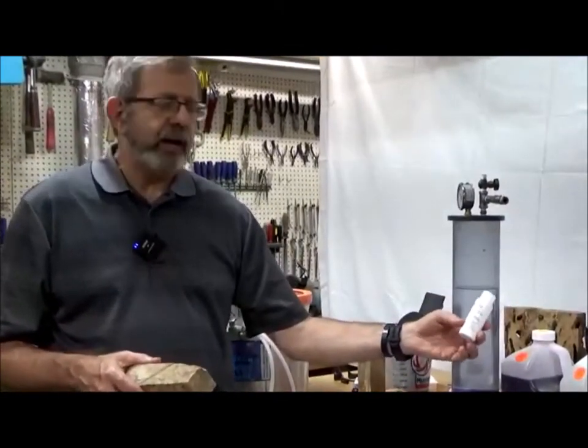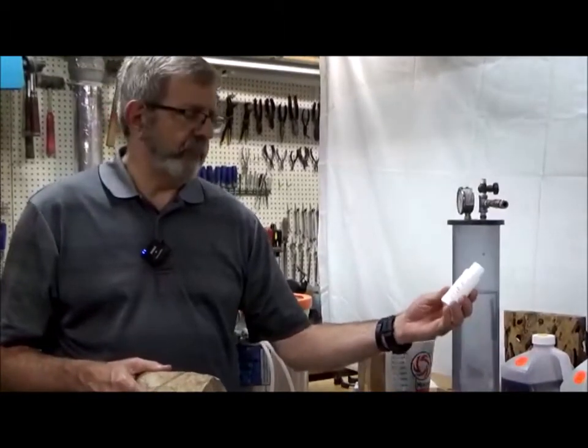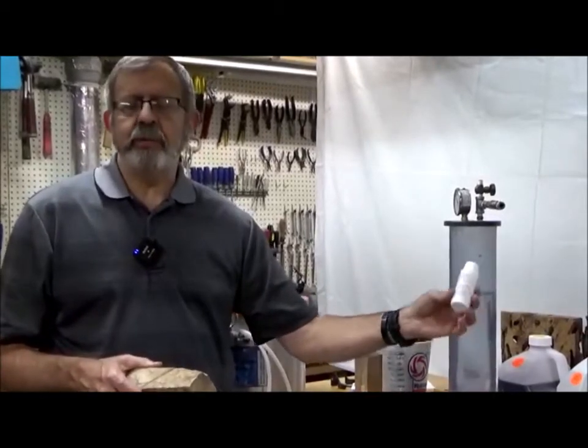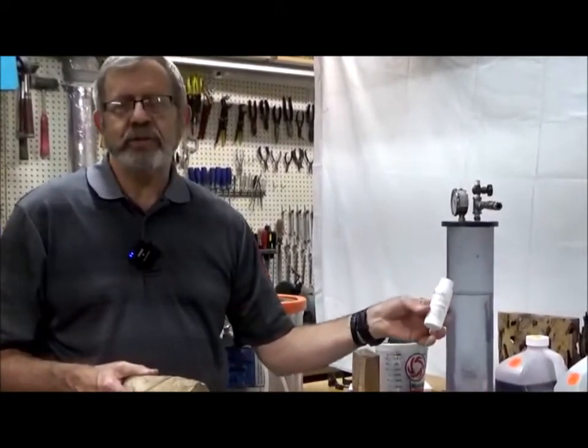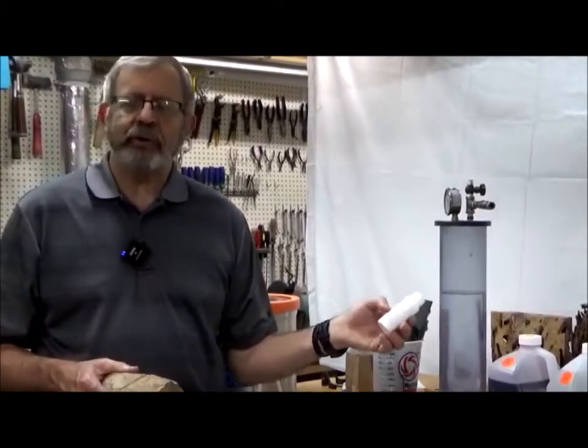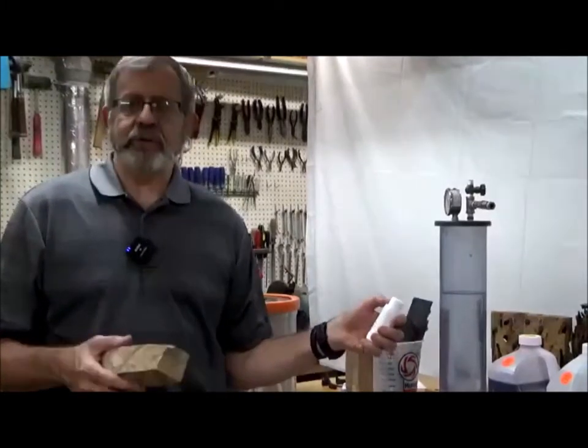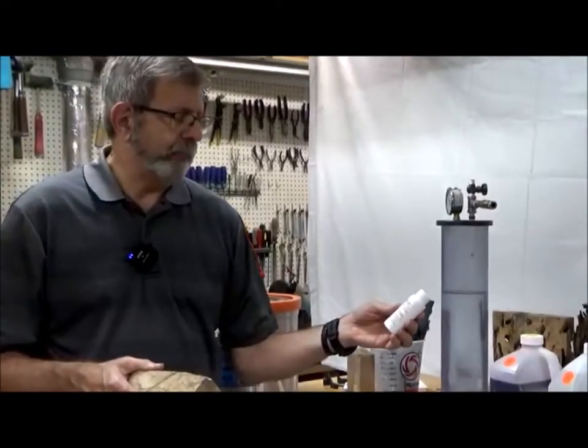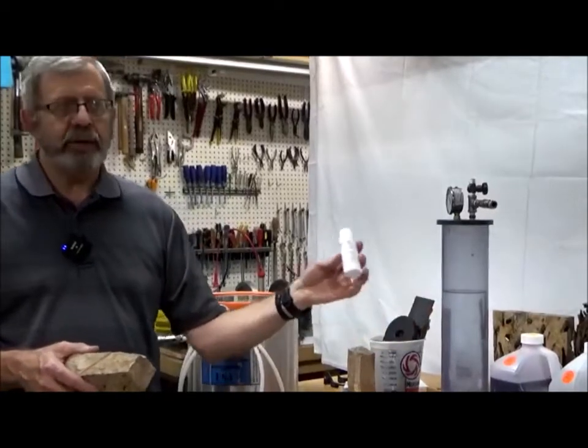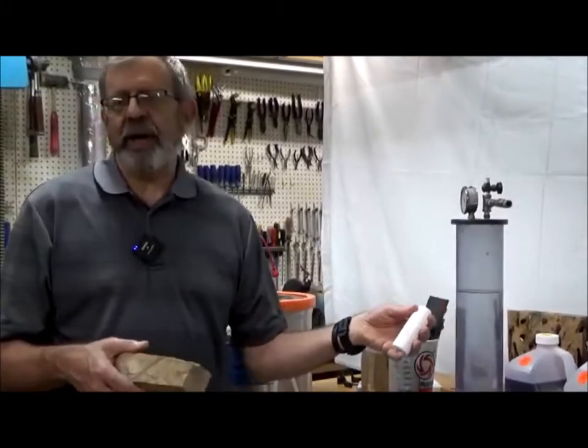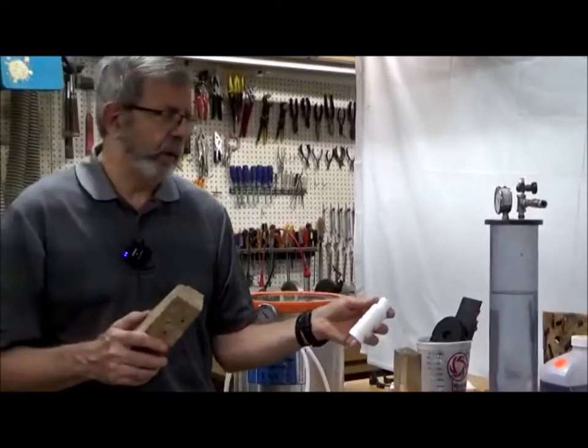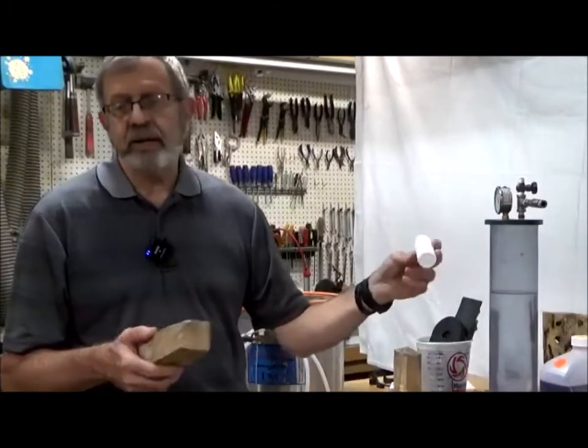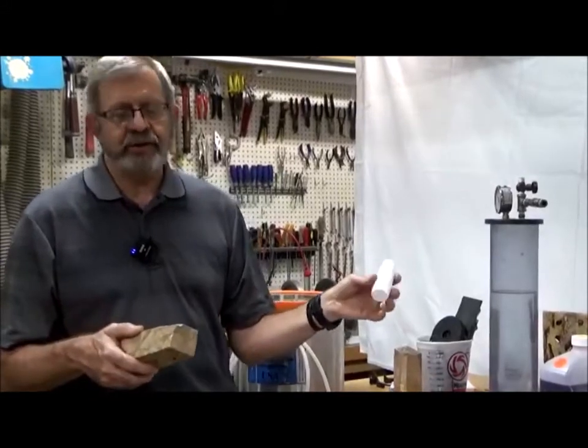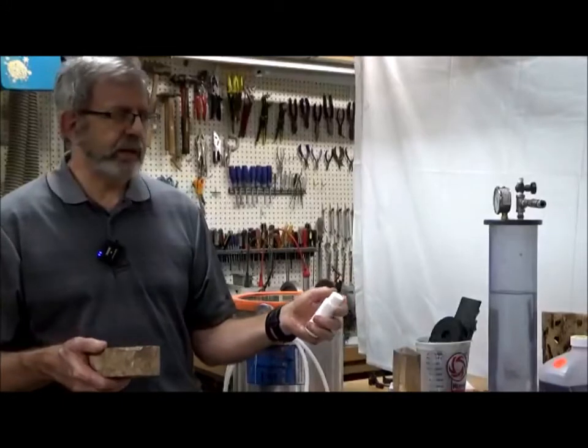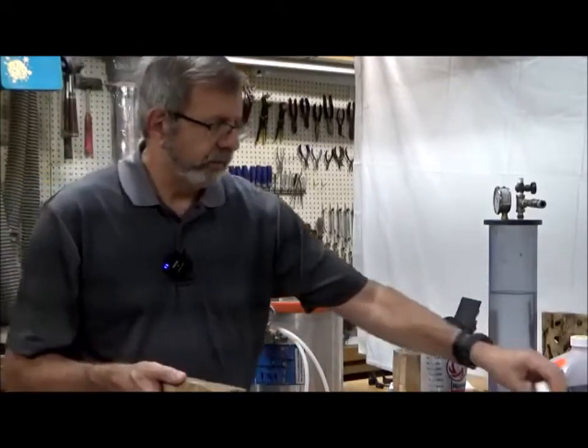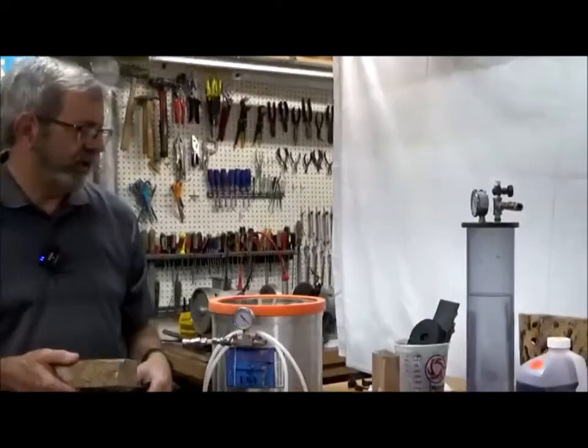But when you buy it by the gallon, it does have to be activated. If you buy smaller quantities, it comes already activated. But you have to add this little bottle to the gallon and mix it before you use it. And the advantage is that once cactus juice is activated, it cannot be stored in a temperature greater than 85 degrees, or it'll start to go on you. So you don't want to do that. When you buy the gallon size, it hasn't been activated, so it doesn't matter if it gets too hot during shipping, particularly during the summer months. But once you activate it, even in your own shop, if you're in an unair-conditioned space, you're going to want to keep that in the house or someplace where it's not going to get over 85 degrees or it will go bad. But that's the material that I use.